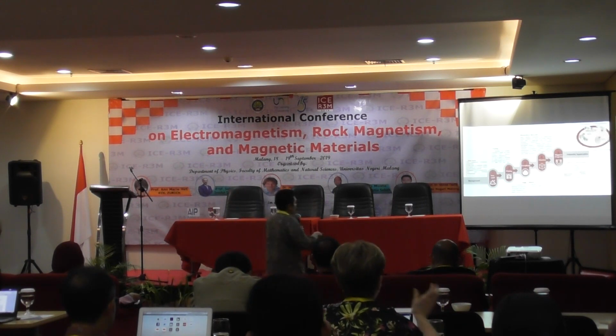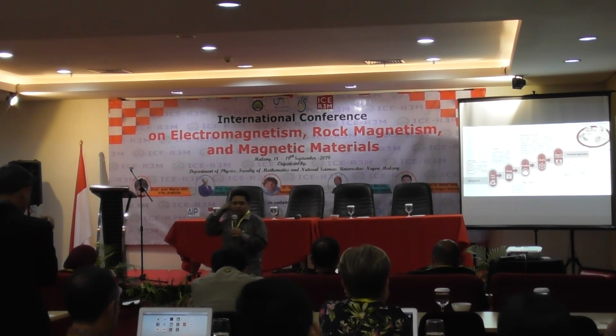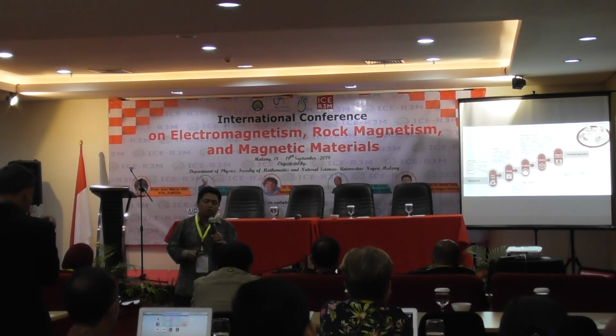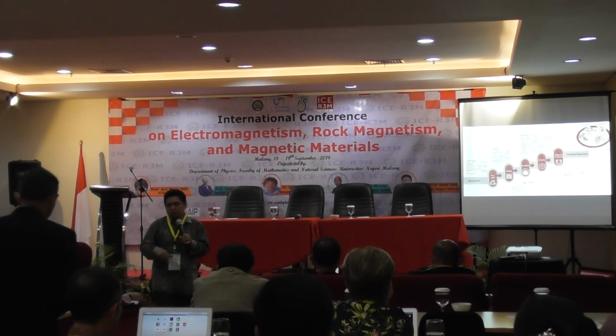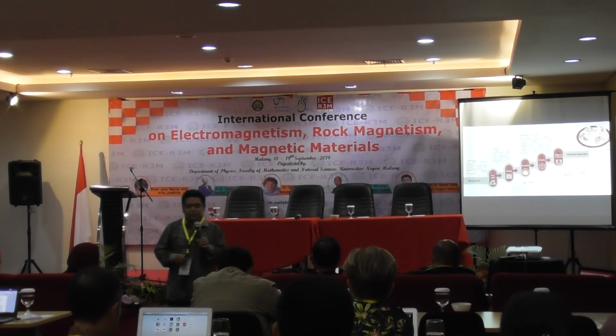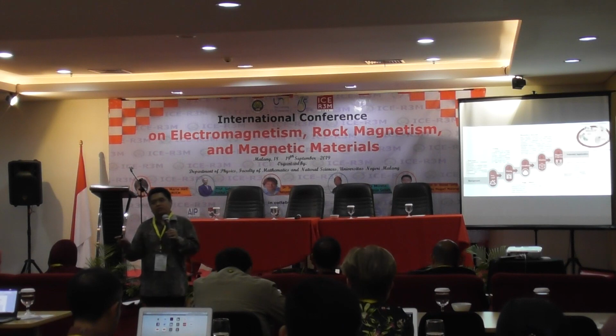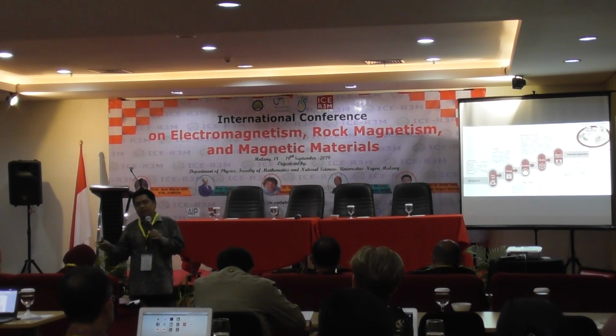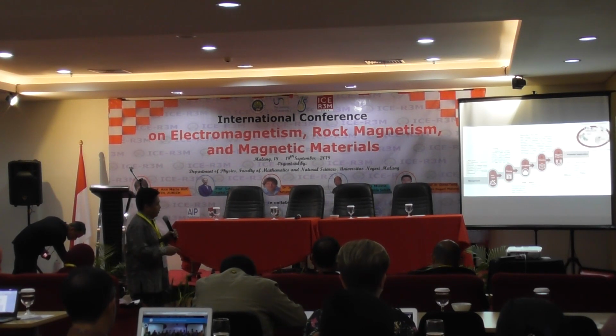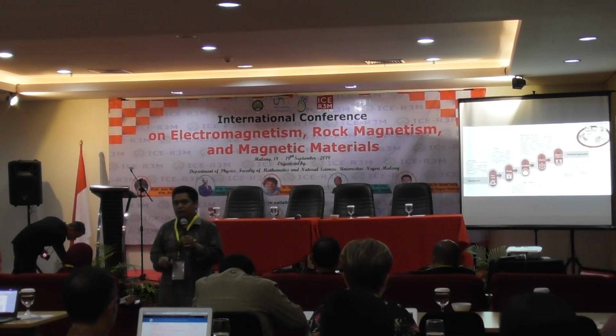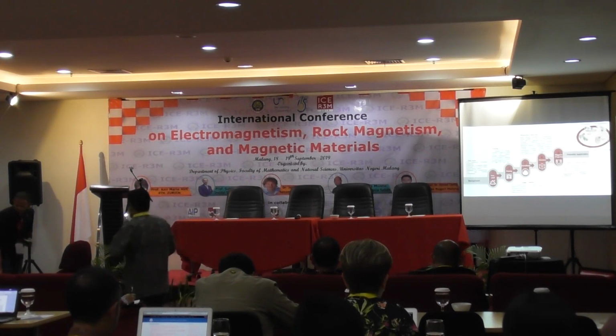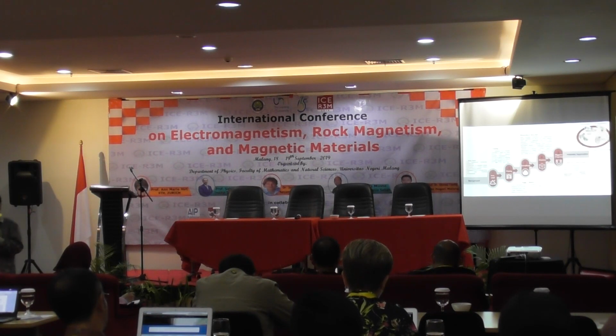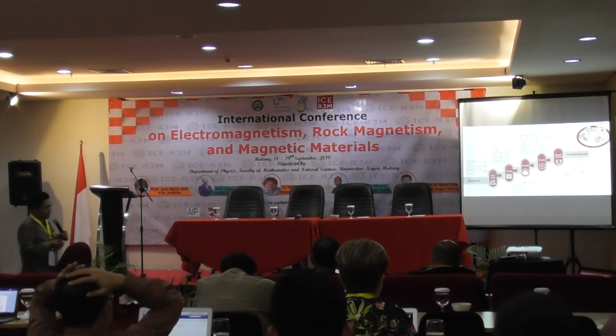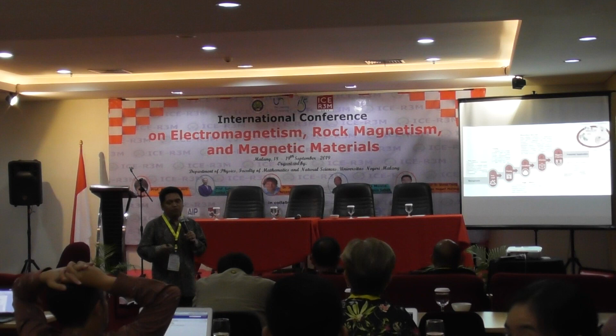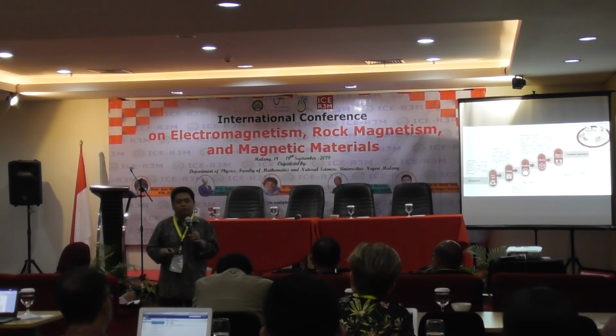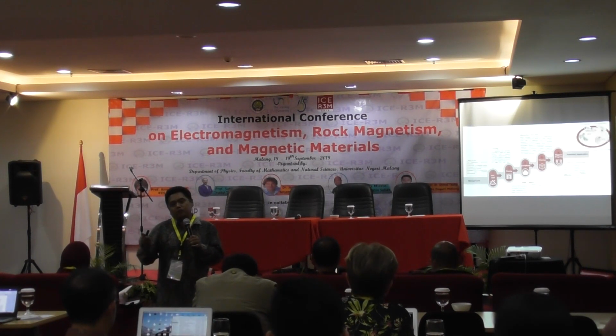Therefore, in our research group, we explore the iron sands to produce some nanoparticles, for example nanopowder and ferrogel, and also magnetic fluid, with methods like co-precipitation, ultrasonic, and a combination of electrospinning, co-precipitation and ultrasonic to produce high purity magnetic nanoparticles. We know that the price of ferrite nanoparticles is very expensive, but in our laboratory we can produce them with a simple and fast method using natural iron sand. For at least 10 years we have developed several methods to synthesize them, and we have more than 10 patents granted about nanoparticles from iron sand.